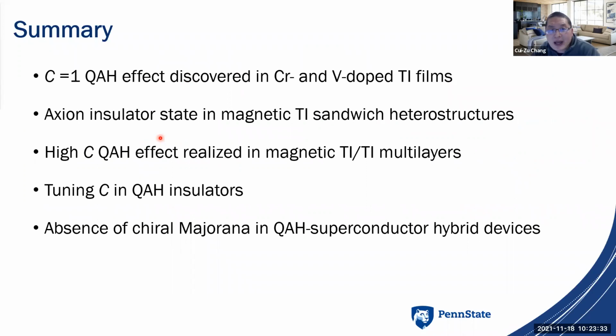And here we come to an end with the summary. We are the first to realize the quantum anomalous Hall effect in chromium and also vanadium doped films. And we fabricated the magnetic TI sandwich structure, and we observed the axion insulator state for the first time. And we fabricated magnetic TI and TI multilayer structures, and we realized high Chern number quantum anomalous Hall insulators. And by tuning the chromium doping level and the thickness of the middle magnetic TI layers, we could tune the Chern numbers in the quantum anomalous Hall insulator layers.